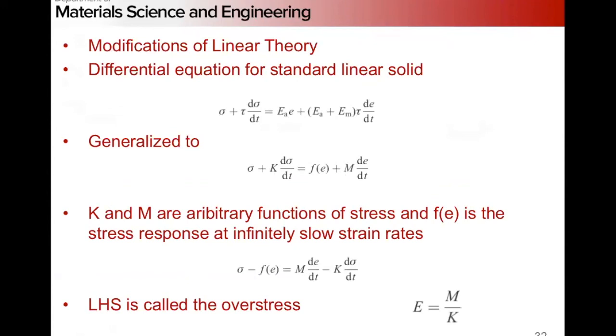So these K and M are functions of the stress. This is the stress response at very low strains, right? At essentially infinitely slow strain rate, right? So you have to pick a model for this, right? And this difference between the applied stress and the infinitely slow stress response is what's called the overstress, right? And our instantaneous Young's modulus is this M over K of these coefficients here. And we call this left-hand side the overstress,